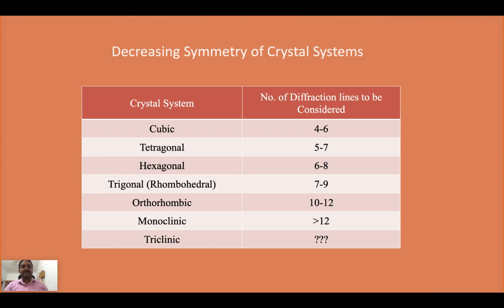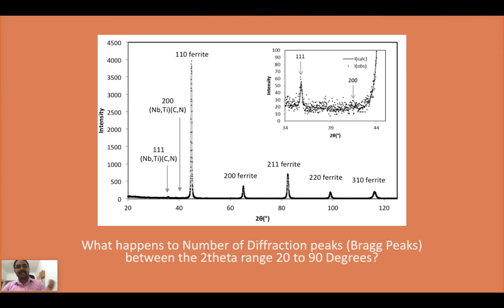You can see it is a cubic system, because when you have a cubic system, all the equivalent planes are producing one peak only. So the number of peaks gets reduced. Just by seeing the number of peaks in your diffractogram, I can say which Bravais lattice it belongs to. It is a rough guess, but it will be a good guess.